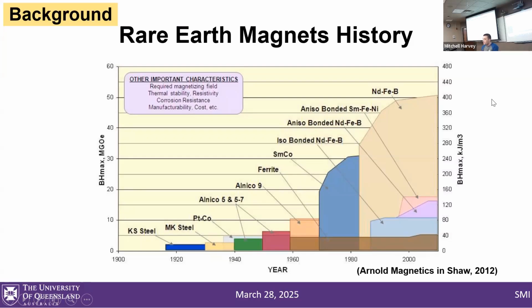So if we want better magnets, we have to use more exotic materials, and that's where samarium cobalt comes in. Samarium cobalt was the first generation of rare earth magnets to gain commercial success, and it was not orders of magnitude, but it was 2 to 3 times better than most of the magnet technology at the time, and it retained that status for multiple decades until we discovered neodymium iron boron.